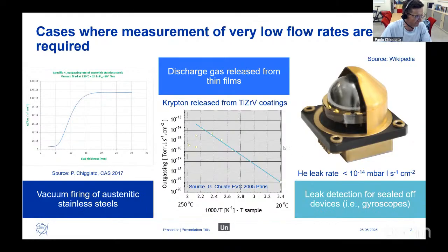Now, the point is that the techniques that are in general used for the measurement of outgassing rate do not work for such values of outgassing rate. The very standard one is the accumulation method, where you monitor the pressure continuously during the accumulation of the gas. In general, you have a linear increase for gases that are not absorbed by the wall of the system. And the system has some intrinsic limitations.